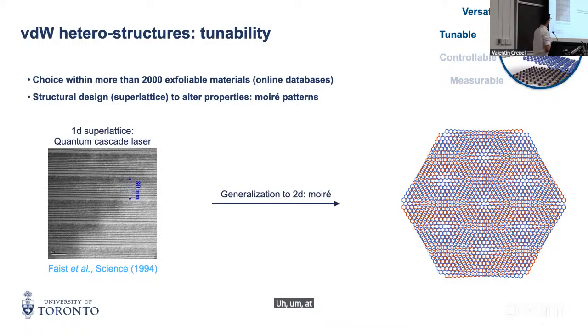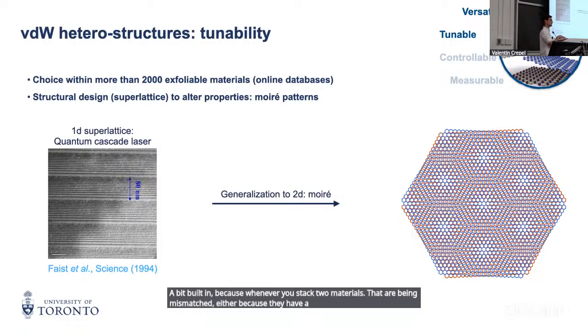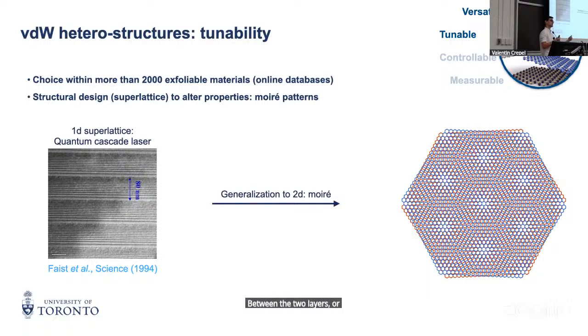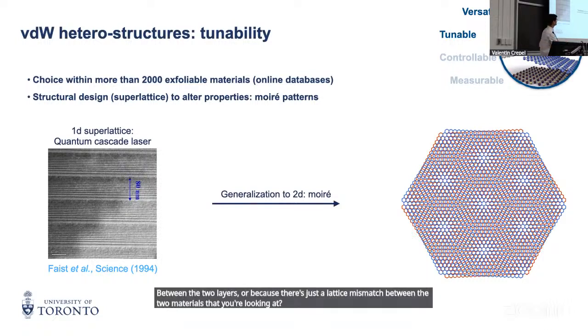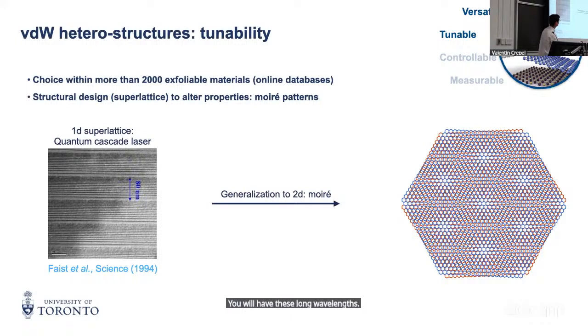And very fortunately for us, 2D materials basically have also their version of superlattices built in, because whenever you stack two materials that are a bit mismatched, either because there's a twist between the two layers, or because there's just a lattice mismatch between the two materials that you're looking at, you will have this long wavelength moiré pattern that will appear. So these are interference patterns made by the lattice of the bottom layer and the top layer. And this naturally arises.